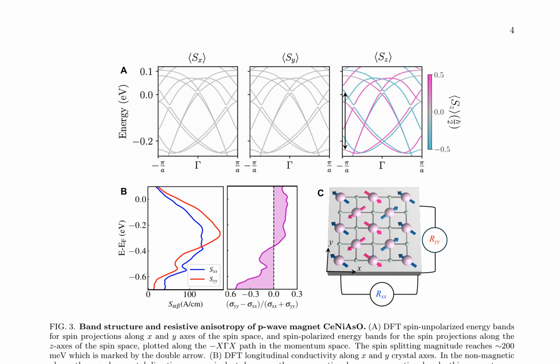The spin-splitting magnitude reaches approximately 200 meV, marked by the double arrow. The DFT longitudinal conductivity along the x and y crystal axes is also shown, highlighting the unconventional p-wave magnetism breaking the symmetry, as evident from the plotted anisotropy of the conductivity. The proposed experimental geometry for measuring the spontaneous resistivity anisotropy is illustrated in Figure 3c.